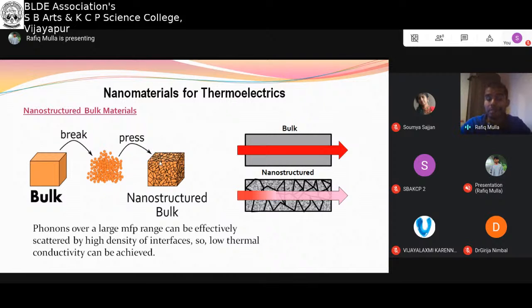In fact, the Seebeck coefficient can be improved in such materials because of these interfaces and some nanoscale structures in the material. Quantum confinement effects still exist, but are very dilute in nature. Because of that, a small improvement in the Seebeck coefficient can be observed in nanostructured bulk materials. So here there is a small improvement in Seebeck coefficient, but a significant reduction in thermal conductivity can be achieved in these kinds of materials.